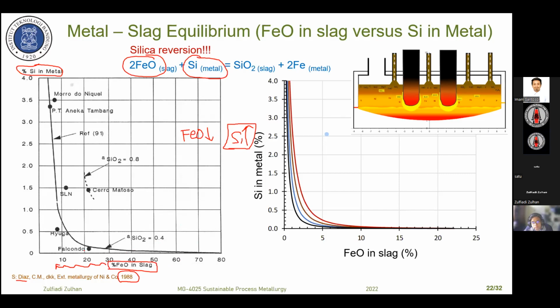You see here, the maximum iron oxide at that time is around 22%. There is no plant in the world operated at an iron content of more than 30%, because it's very aggressive to the refractory material. So they keep the iron oxide content at less than 25%. So you have low iron oxide, according to this thermodynamic equilibrium. So we have high silicon content.